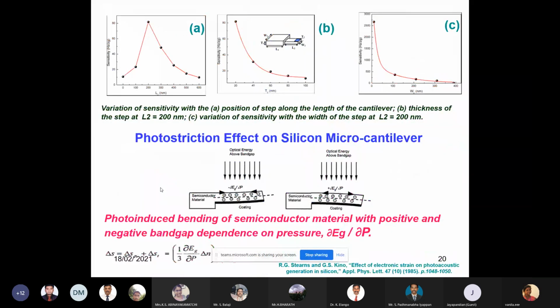And the next one, the top one, is discontinuity, removing some part of the cantilever. On the left-hand side, we remove lengthwise, then widthwise, then thickness-wise: A, B, C. In the first graph, you can see at 200 nanometer, a fantastic variation, very high mass sensitivity. Then it clearly shows that cantilever tailoring can support going for a high sensitivity cantilever application.